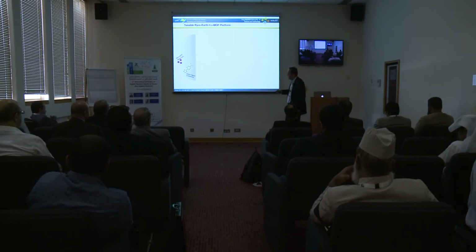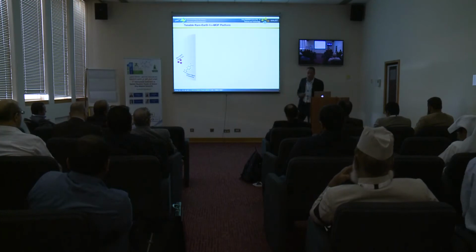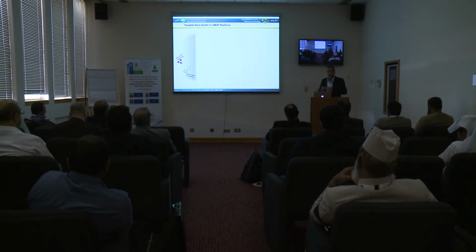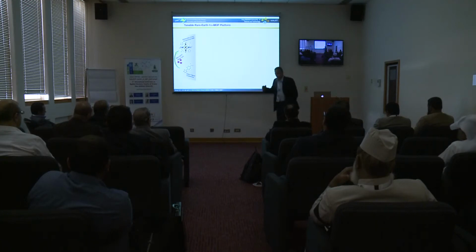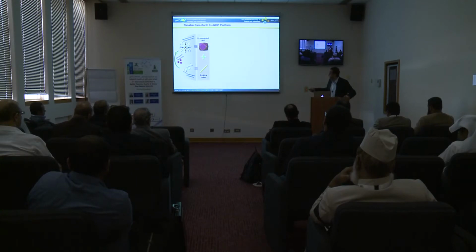This is one example where we introduced a polarized ligand that has tetrazoles, carboxylate, and fluorine groups, so we can enhance the interaction with CO2. We explored many metals. That allowed us to discover this cluster here that has hexanuclear lanthanides bridged by 12 ligands. But what's interesting is this gives you a building unit that's 12-connected and the linear linker.